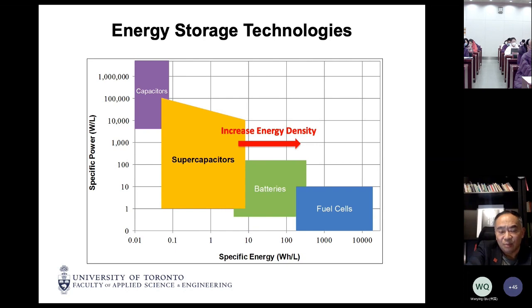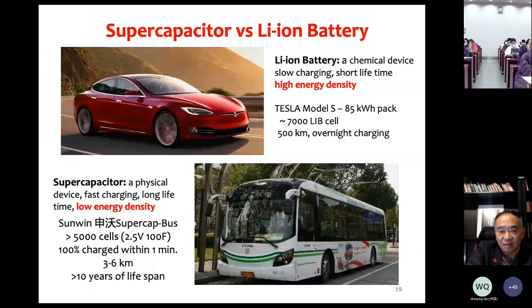And the Tesla is powered by lithium-ion batteries because of their high energy density. But this is the bus, which is powered by a supercapacitor, and because a bus has lots of space, in this case you can charge this supercapacitor within, say, minutes. Okay, but it can only drive 3 to 6 kilometers. Another advantage of a supercapacitor is its lifespan, which is over 10 years. You can charge it 500,000 times, okay, which is much longer than lithium batteries, which is about, let's say, 4,000 cycles.